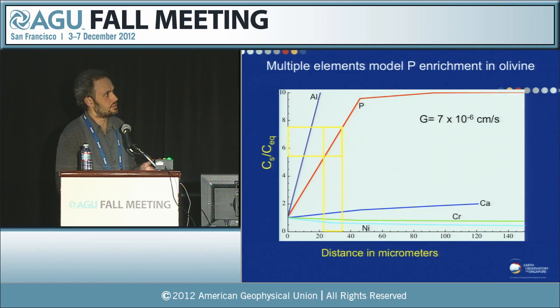So if you do the model, this is what you get. This is distance from the moment that the crystal started to grow at this rate. What I was trying to achieve is that at about this distance, 20 to 40 microns, we have an enrichment of phosphorus, which is a maximum, about 6 or 7. So this is a plot of a fit of the phosphorus maximum. And for doing this, we require this type of growth rate, which is relatively fast.